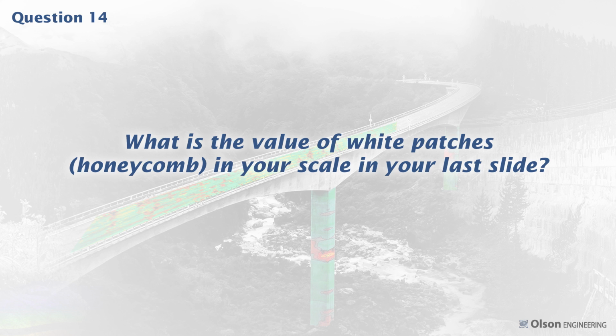Okay, what is the value of white patches, honeycomb, in your scale in your last slide? Dennis will talk about that. I can answer that. The purple areas in that last slide were actually the honeycomb areas. The white areas were areas where we were on top of, say, wood or cutouts or holes where there was no data. The data was invalid, and we just threw that out. The red areas were shallow cracks. The purple areas appeared to be deeper than the concrete could possibly be, and therefore indicated a honeycomb or void.